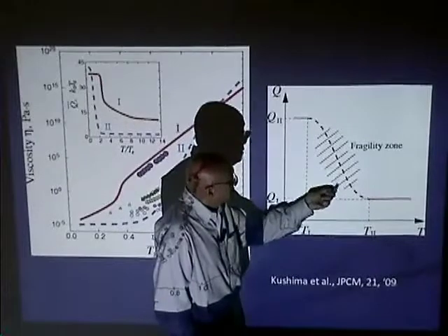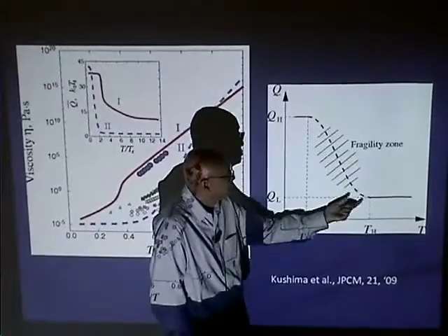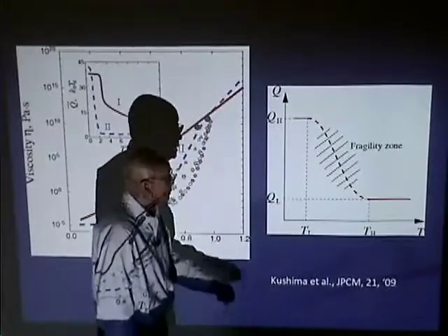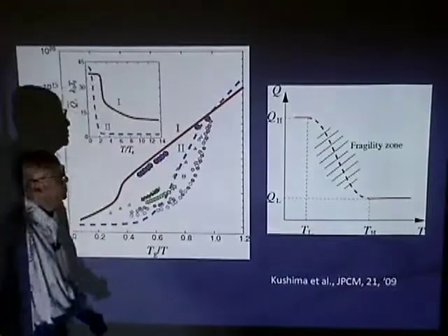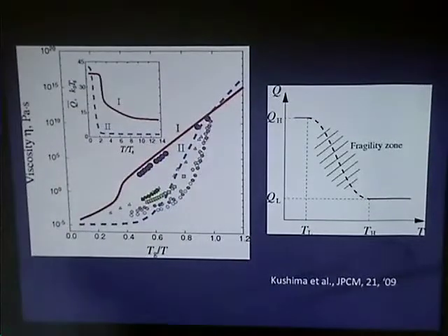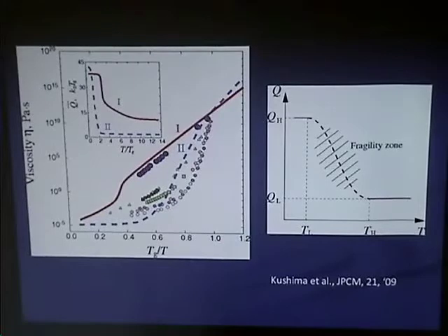Well, this fragility zone has a certain extent, so when that extent goes to zero, you just hop from low to high. The Q here, right - QH and QL - on your viscosity plot are slopes. So you can cross from a low slope to a high slope without having to go at a higher slope still in between.